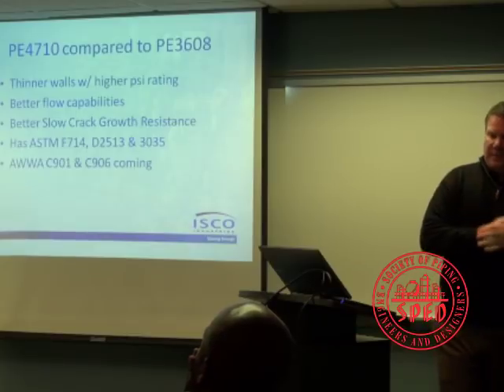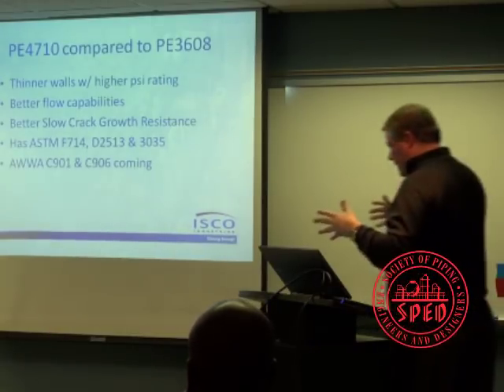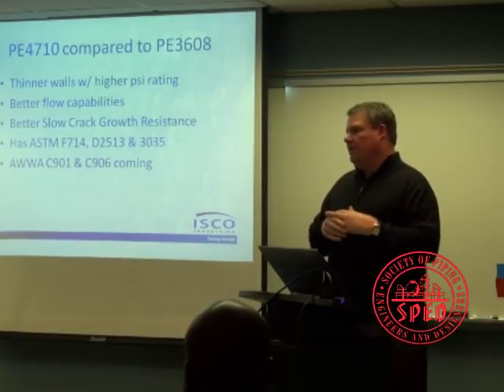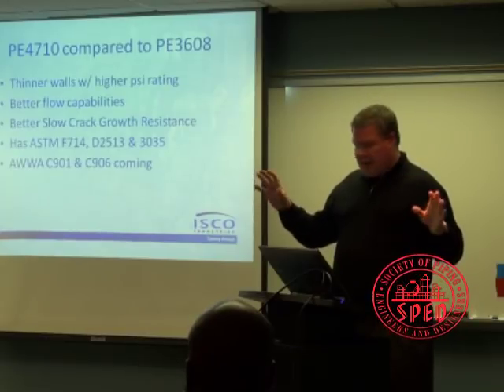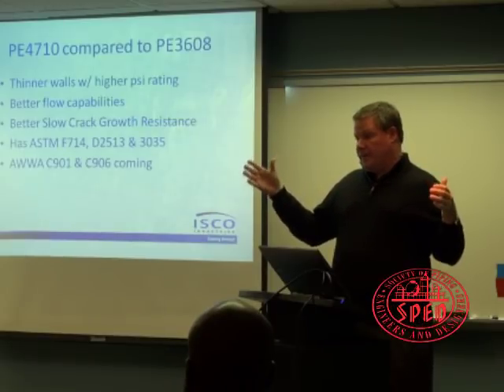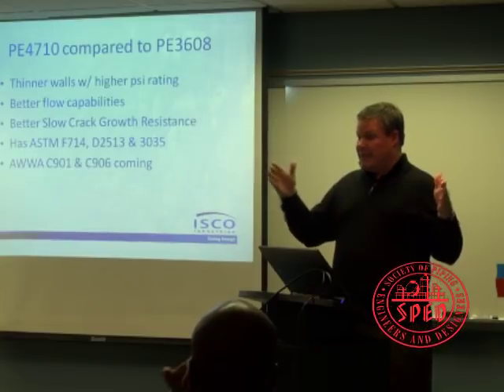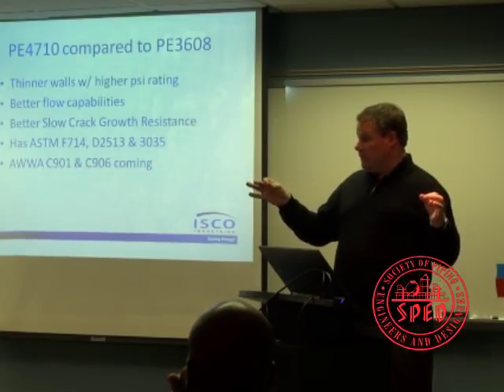So the rule of thumb that's out there is called 1-10-100. If I take 100 feet of pipe and fuse it, and we're sitting here in the nice summer heat of Louisville, and it goes from 80 degrees to 90 degrees, non-restrained, just sitting out in this parking lot, it will swell 1 inch for every 10 degrees at 100 feet. That gives you the idea. If it goes from 80 to 70, it's going to shrink 1 inch. So it's called the 1-10-100 rule.